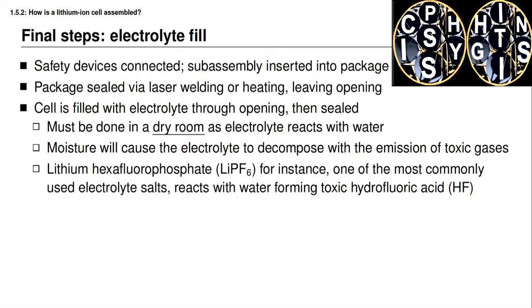toxic gases. And furthermore, lithium hexafluorophosphate, or LiPF6, which is one of the most commonly used electrolyte salts, reacts with water and forms toxic hydrofluoric or HF acid when it does so. And this HF acid can cause the electrode materials to dissolve or disintegrate inside the cell over time, which leads to capacity loss. So we highly desire to avoid that, or at least to minimize that. And we do so by injecting the electrolyte into the cell inside of a dry room environment.